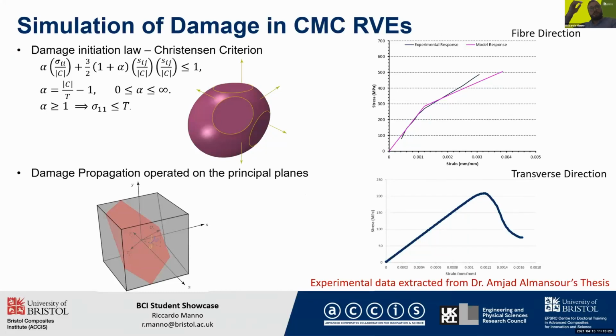Finally, we developed a continuous damage mechanics model for Abaqus for the study of mini-composite response based on Christensen failure criterion. Minicomposites are basically single fibrous tows, typically used as representative specimens in the experimental analysis of CMC. In this case, we performed some comparison in the fiber direction between numerical and experimental tests, as you can see on the top right-hand side of the slide.